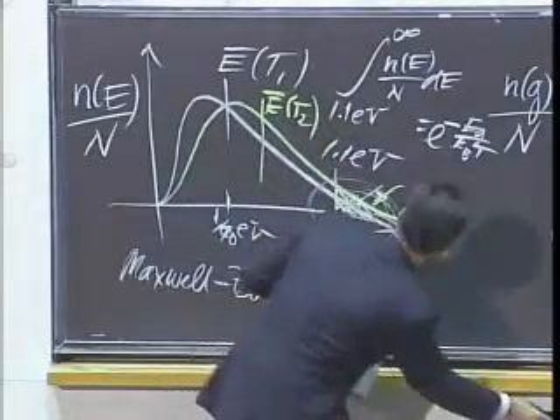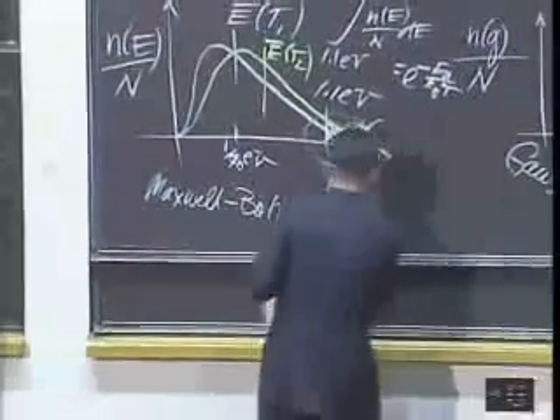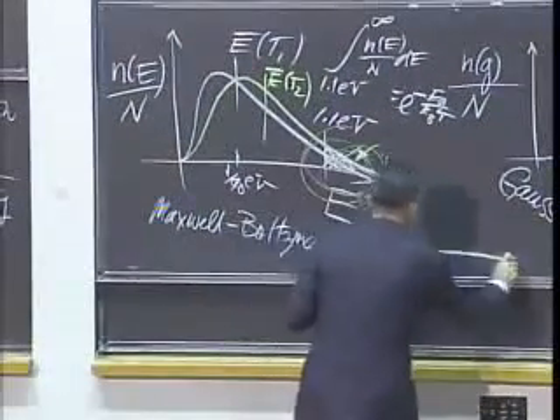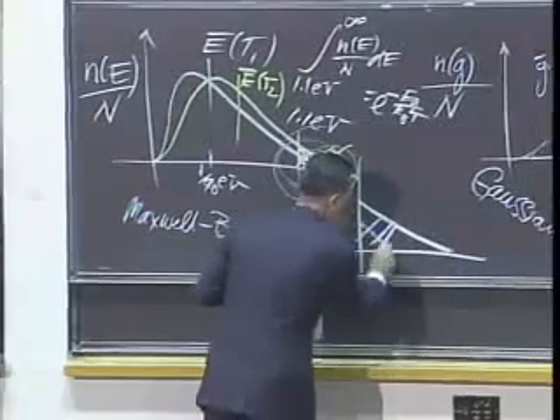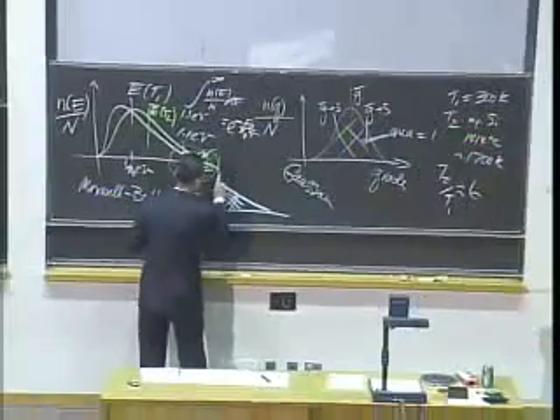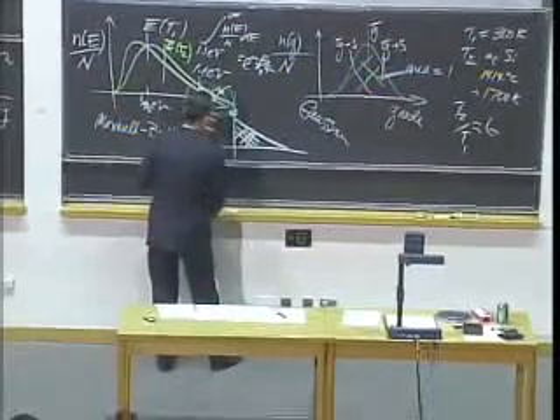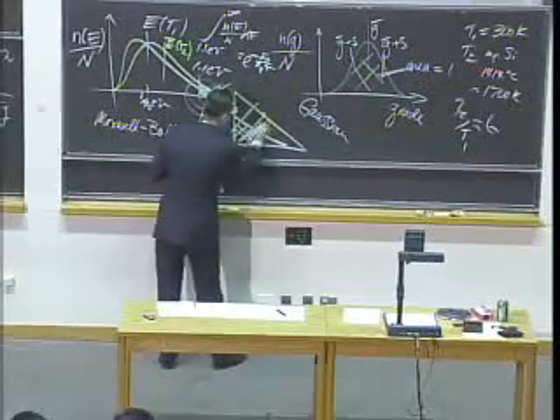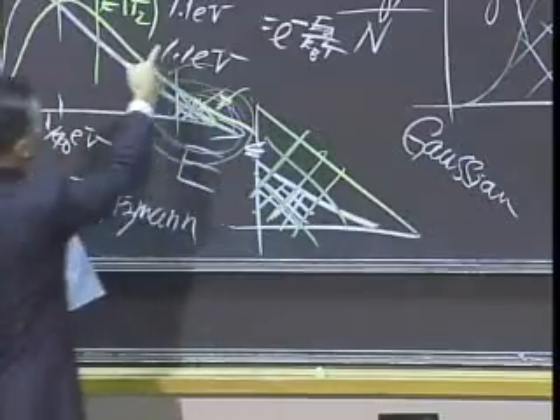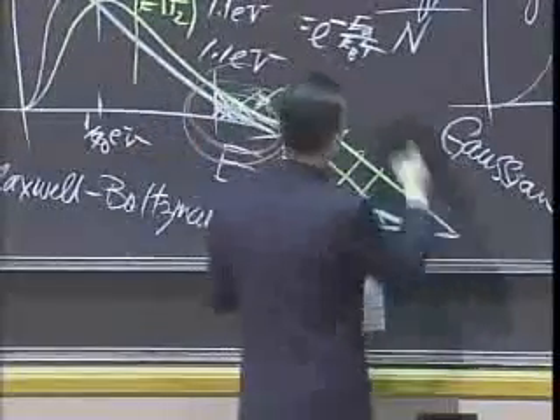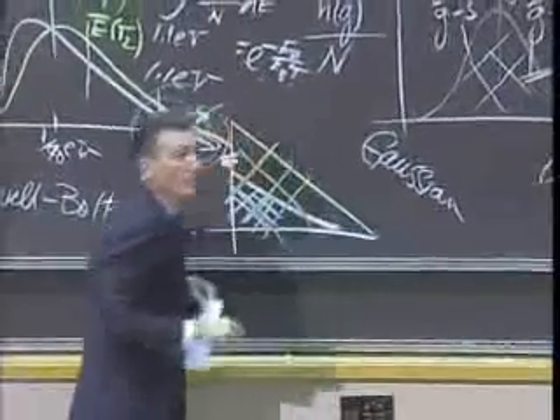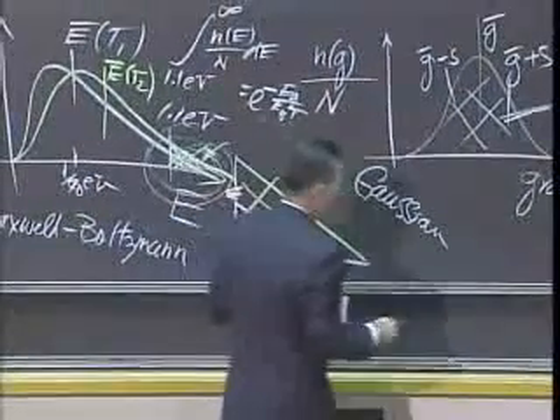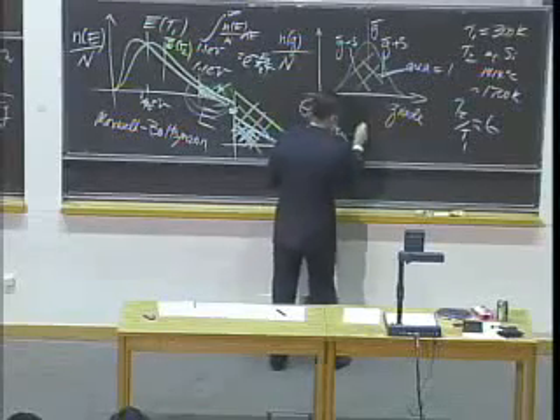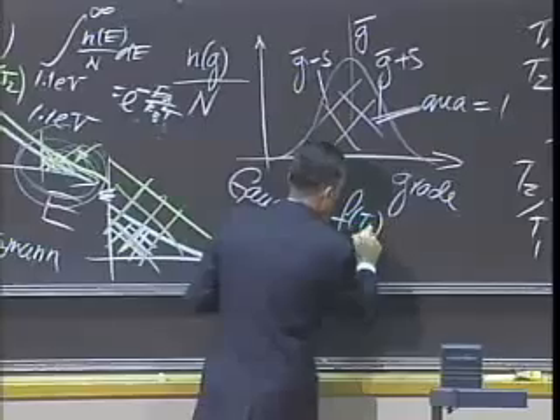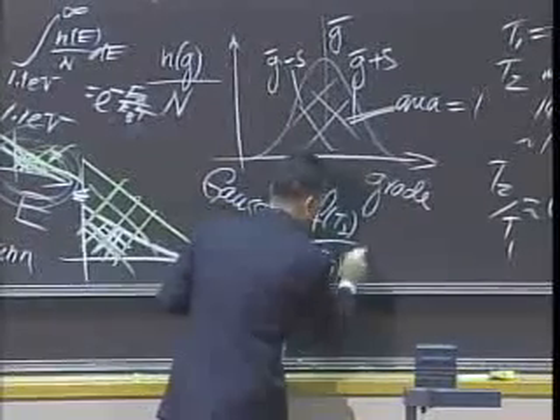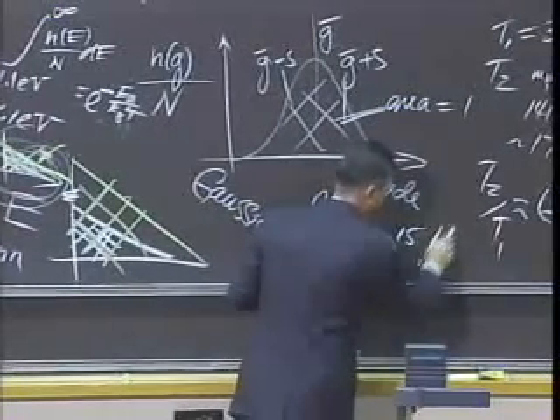I'm going to blow this up. What we're really looking at is the difference between the area here at room temperature, and then, not to scale, the area under the green curve. And when we use this relationship, e to the minus band gap energy over kT, we find that the fraction at T2 divided by the fraction at T1 comes out to be 10 to the 15th.